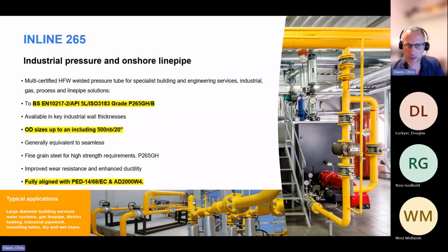When we get to the larger diameter pipework, again, the API reference is in there because the walls tend to be related to the schedule 20, schedule 40, but you can notice that instead of a 235 grade, we're actually a 265 grade, so a stronger grade of steel. And the reason for this is it allows us to go to thinner walls and still maintain the service life and pressure integrity. But that stronger grade of steel allows you to basically achieve that without adding additional cost, additional mass, and additional CO2. You can see that the 10217 is referenced because, again, the PED, European Pressure Equipment Directive as well. And obviously the ISO 3183 is the equivalent to the API.